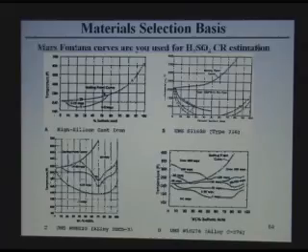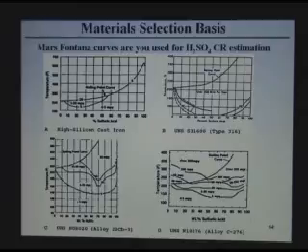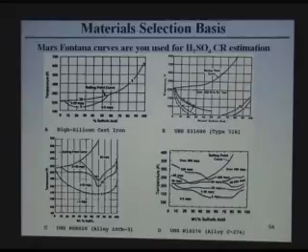And these are also corrosion rates of different materials. This high silicon iron, which we used a lot in sulfuric acid. This 316 stainless steel gives some protection, but not 100%. Alloy 20 is the workhorse for the sulfuric acid applications, as well as Hastelloy alloy, and Inconel 625 also is a good material for sulfuric acid.